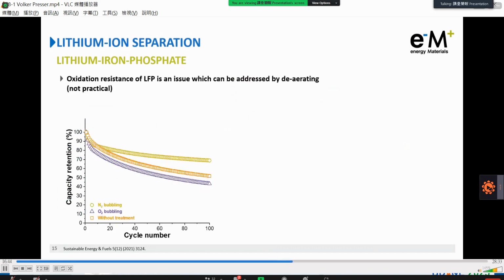One reason why a lot of scientists don't like to work with LFP and prefer lithium manganese oxide or other oxide systems is the instability of LFP in oxygen-containing aqueous electrolytes. One possibility to overcome that limitation is by bubbling, removing the dissolved oxygen, and we reach much higher capacity retentions of around 100 cycles. However, this is very often not practical because it involves a lot of water treatment for deaeration.